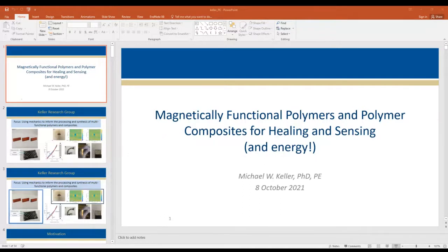As we increase pressure, we start seeing a decrease in the percentage of specimens exhibiting 100% heal. Things that we're working on here are trying to improve the healing chemistry, adding adhesion promoters and other things to improve the bond that we get, and improving the design of the channel network to try to be more realistic. We've gotten to the point now where we're basically making material to go into a commercial valve to do some semi-pilot testing. Anyways, we were pretty psyched about these results. Hopefully we'll get them into a membrane or into a system and help reduce the amount of fugitive losses that we're seeing.